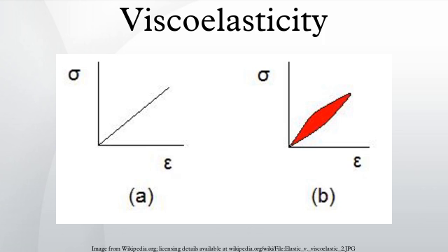Each model differs in the arrangement of these elements, and all of these viscoelastic models can be equivalently modeled as electrical circuits. In an equivalent electrical circuit, stress is represented by voltage, and strain rate by current. The elastic modulus of a spring is analogous to a circuit's capacitance and the viscosity of a dashpot to a circuit's resistance. The elastic components, as previously mentioned, can be modeled as springs of elastic constant E, given the formula.